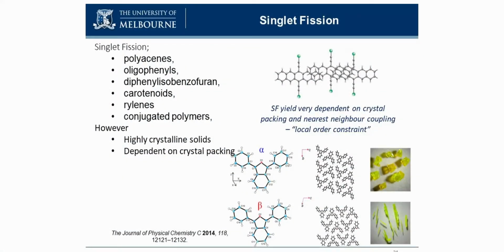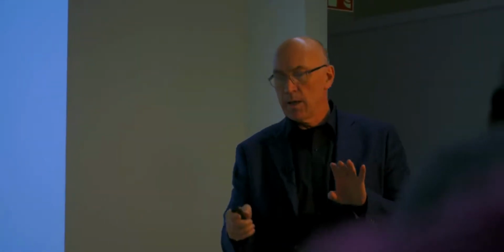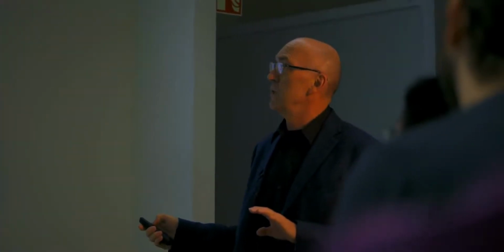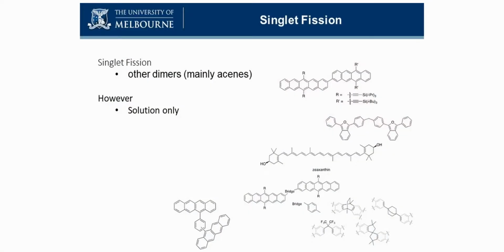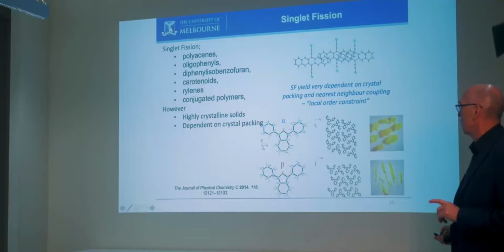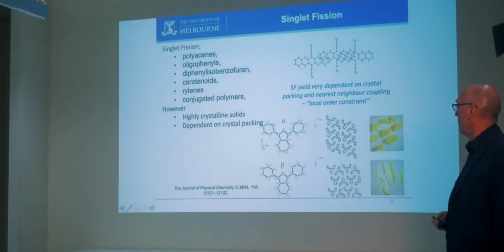So if we look at what's in the literature, things that do singlet fission: polyacenes, so tetracene, pentacene, oligophenyls, these diphenylisobenzofurans, these carotenoids and these rylenes and some conjugated polymers. But because we need two molecules close together, we need highly crystalline solids. And so effectively, the singlet fission yield is really dependent on the crystal packing because we need this overlap between the orbitals of the two molecules. However, that doesn't always work well because it also then depends on the polymorph. And so most of these materials up here, they may have two polymorphs, and this is the diphenylisobenzofuran. One polymorph or one crystal structure is singlet fission active, the other one isn't.